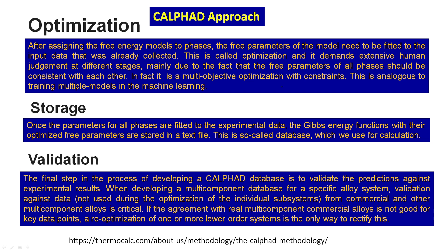The final step is validation — checking whether your optimized data satisfies previous experimental results. For a multi-component database, validation against data for commercial multi-component alloys is very critical because databases are often not available or not perfectly optimized. If agreement with real multi-component alloys is not good at key points, you have to go back to optimization for one or more lower-order binary or ternary systems.